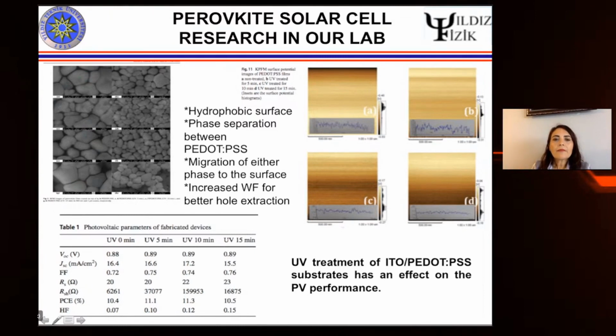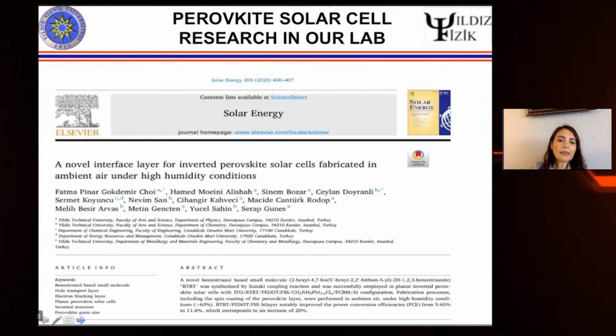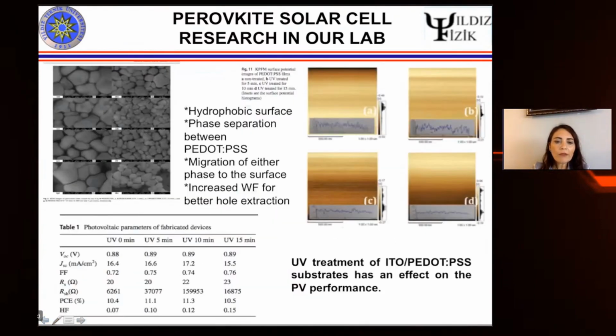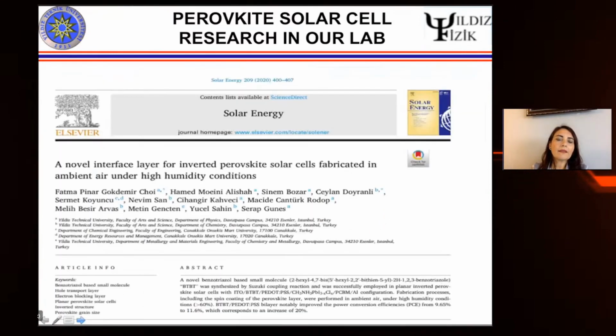And because of the UV radiation, we have realized that there is a phase separation between the PEDOT and PSS, and either phases can migrate to the surface. And also, the work function of the PEDOT:PSS is increased. Of course, we have to find an optimum way because we exposed them 0, 5, 10, and 15 minutes. The 0 case was the reference case. And after 15 minutes, the cells were not working properly because most probably the ITO and the PEDOT phase was disturbed.